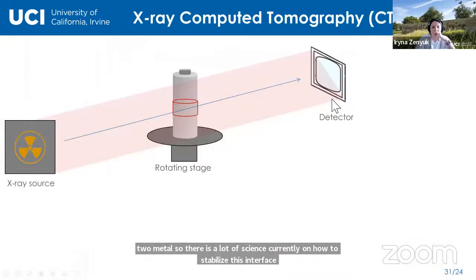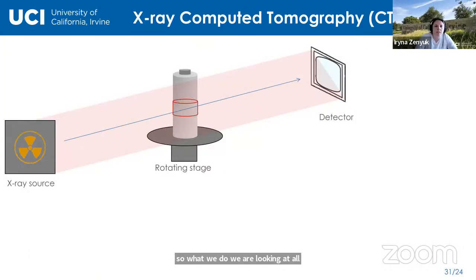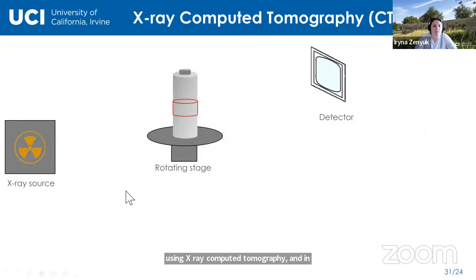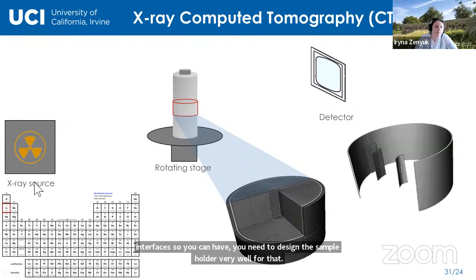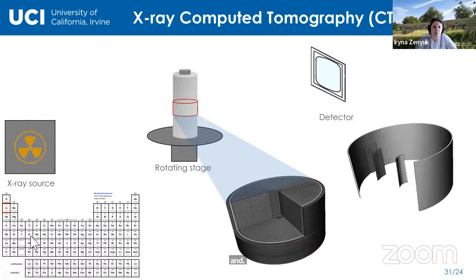So what we do, we are looking at operando cells using X-ray computer tomography. And in this setup, you have X-ray source. You have your battery on rotating stage, and you have the X-ray detector and other optics along the way, depending on whether you use nano or micro CT technique. And from there, you can put just the real battery, but then you're not going to see much interfaces. So you need to design the sample holder very well for that. And X-rays are sensitive to most of the elements, but lithium is very light. So there is a challenge of how do you detect lithium with hard X-ray source.